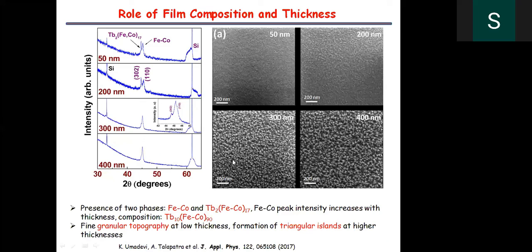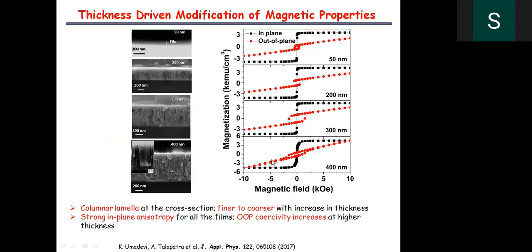Basically, this is the iron-rich composition. As we see from the microstructure at higher thicknesses, we could see perpendicular growth of these column-like structures. In the cross-sectional microstructure, we should see nice columns. As I told you earlier, these nice columns are responsible for producing the out-of-plane magnetic anisotropy.